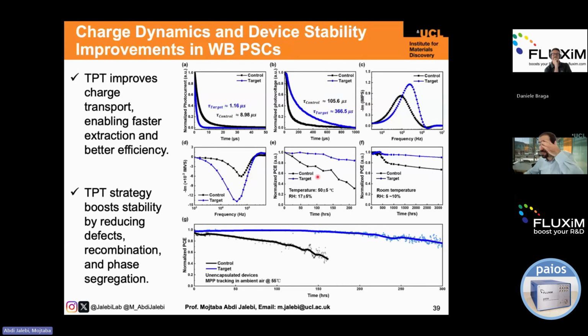And finally, in terms of stability, we have reached better stability for the perovskites with triple passivation versus the control at higher temperature, like over 50 degrees, and also at room temperature. This is for unencapsulated devices at 55 degrees. And you can see that the target is over 80% of its initial performance after 300 hours without encapsulation. And for the control, it's almost reaching 30% of its initial efficiency.